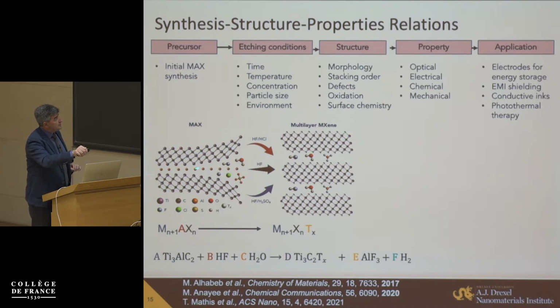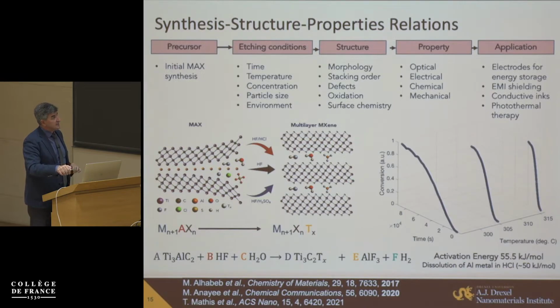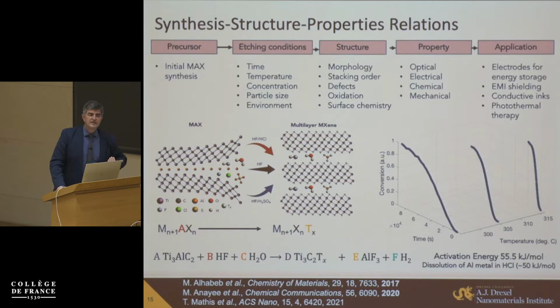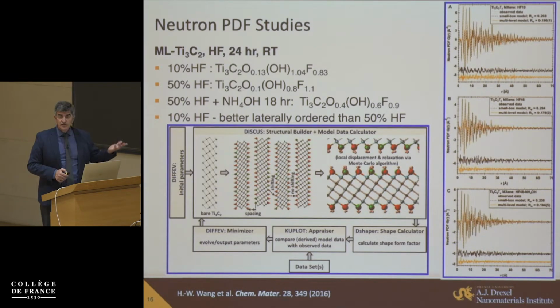So again, we etch, removing this layer of, say, aluminum or silicon. We get intercalation of ions from solutions. And we can control the kinetics, for example, by changing temperature. When etching, you increase the temperature, you require shorter and shorter time to etch. But if you increase temperature further, you start creating more defects. You can remove transition metal atoms from the surface. You get high oxidation states. So all these things interplay. And often you can also get a complex surface chemistry. This is a result, for example, of neutron pair distribution function studies on materials produced using 10% and 50% HF solutions. Now we go to much lower concentrations, usually. And you will see the amount of fluorine increases with increasing concentration.